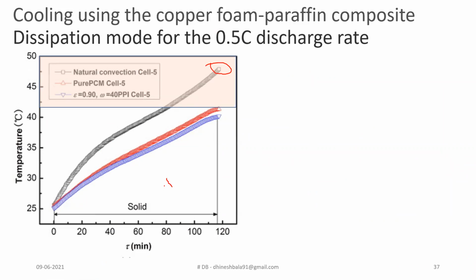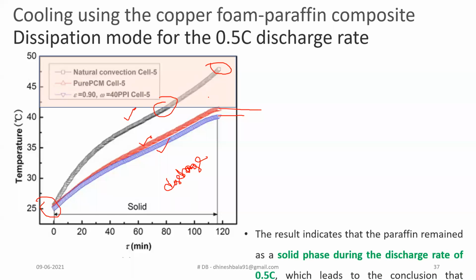So here they have only plotted the discharge plot, because they have neglected the charging cooling and the discharge cooling cycle. Most of the concentration has been placed on the discharge. So if you see it very clearly, from the atmospheric 25 degrees Celsius to 42 degrees Celsius, the temperature pattern of either natural convection, the black one is the natural convection, the red one is the pure PCM, and the violet color is the incorporation of metallic foam to it. So in all the cases, this follows a similar pattern, but once it exceeds 42 degrees Celsius, you can see there is a drop in temperature for the PCM and PCM based metallic foam as compared to the natural convection. So this is the role of phase change material in the battery cooling system.